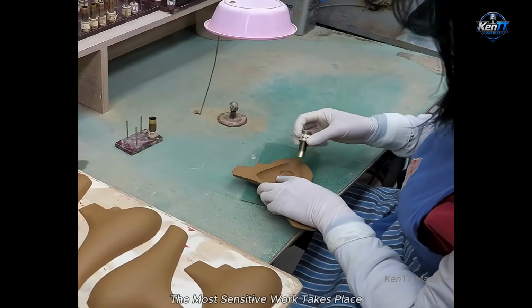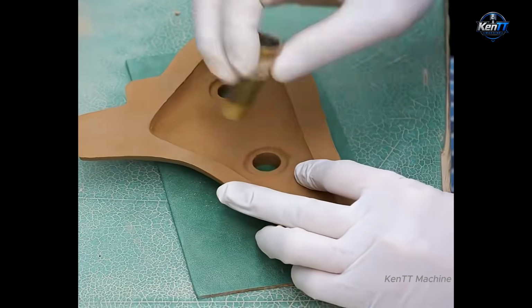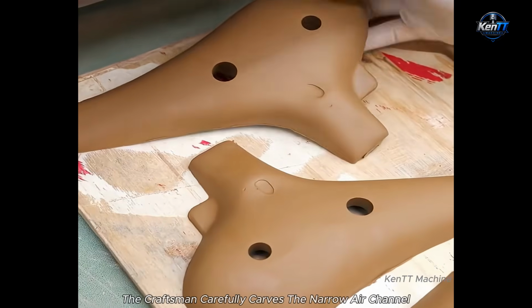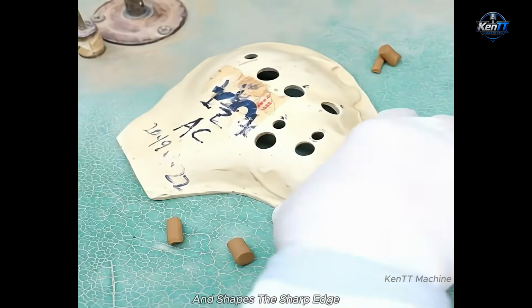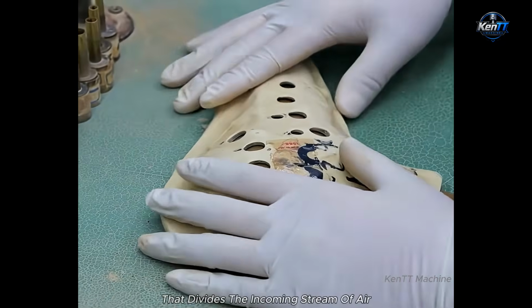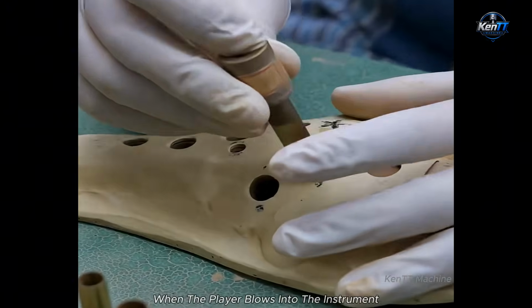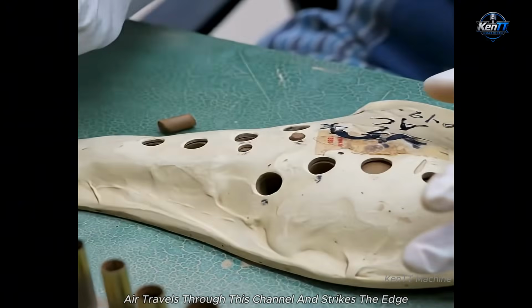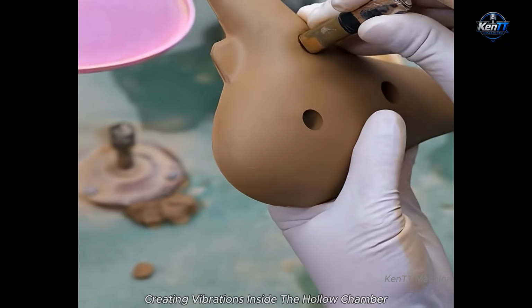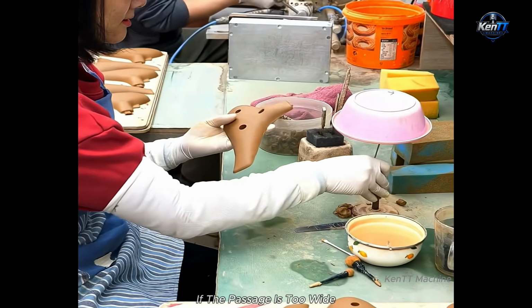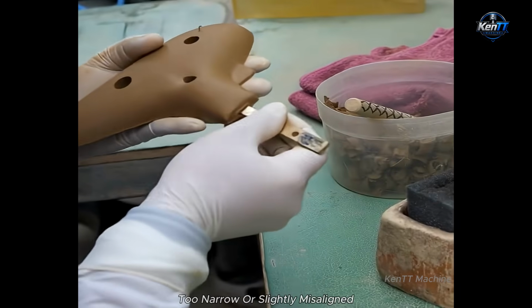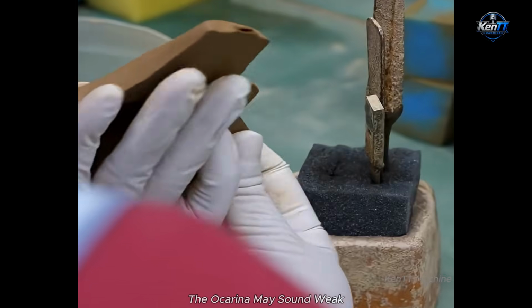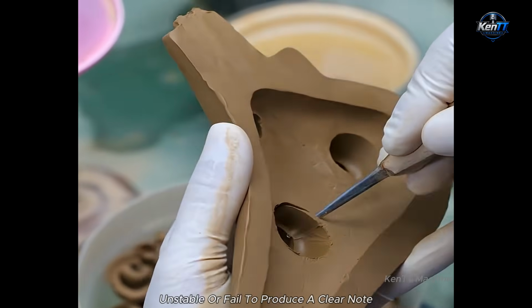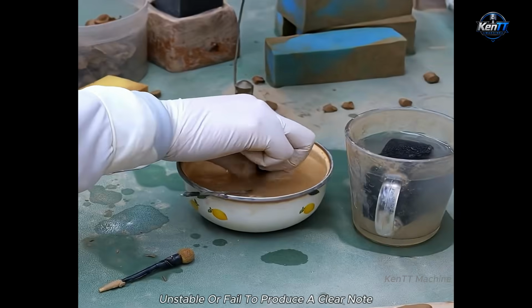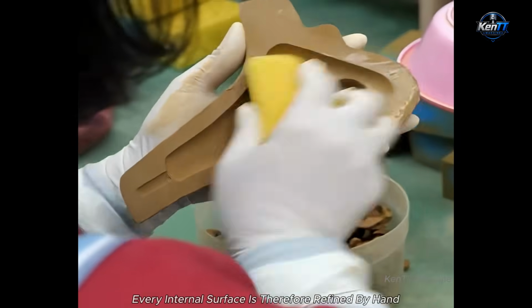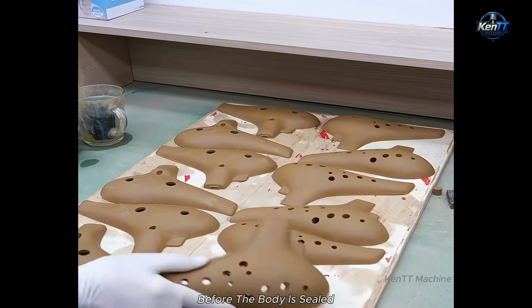The most sensitive work takes place inside the mouthpiece. The craftsman carefully carves the narrow air channel and shapes the sharp edge that divides the incoming stream of air. When the player blows into the instrument, air travels through this channel and strikes the edge, creating vibrations inside the hollow chamber. If the passage is too wide, too narrow, or slightly misaligned, the ocarina may sound weak, unstable, or fail to produce a clear note. Every internal surface is therefore refined by hand before the body is sealed.